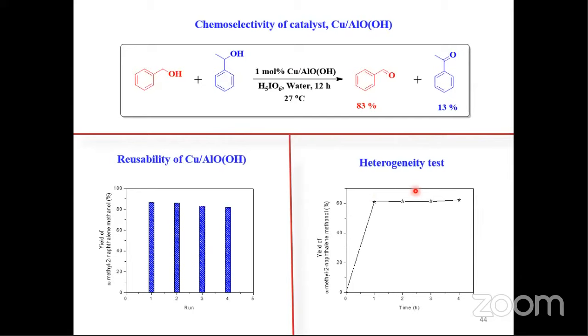Whenever you have a solid support over which you have the catalytically active metal center, during the reaction in the solvent, there is a possibility of leaching of the metal from the support, and then the metal in the solution catalyzes the reaction homogeneously. To see whether it is truly heterogeneous or whether there is any leaching of metal catalyzing the reaction in solution, we have done the reaction, for example, for 1 hour. At 1 hour, the yield of the product is 60%. After 1 hour, the catalyst was filtered from the reaction medium, and the reaction is continued without the catalyst. So once the catalyst is removed, you see there is no improvement in the yield of the product.